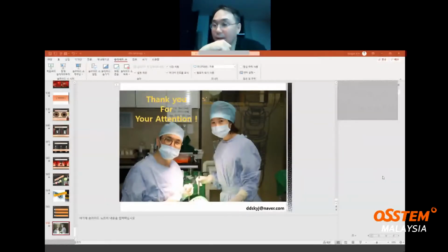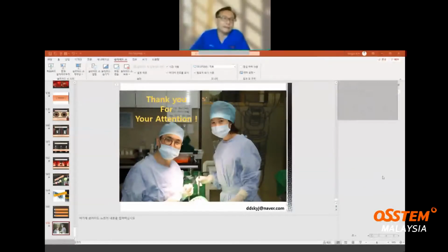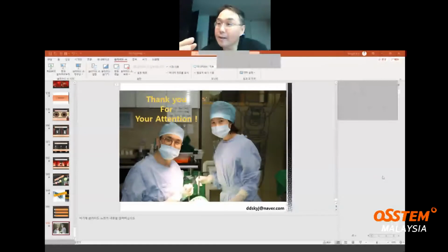How about D1 bone? Is there a problem that you worry about? Because hydroxyapatite had a problem 20 years ago when they do it, right? They delaminate. Does the current one have this problem? Even though this nano size hydroxyapatite particle can be dislodged when placing implant in the D1 bone, the particle size is quite small and can be resolved easily. Right, no need to worry about that problem.